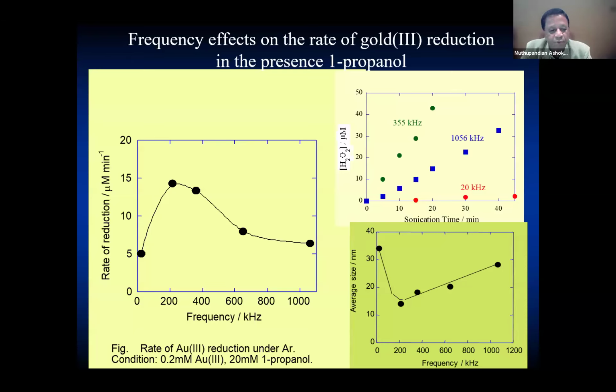So here, what I'm trying to show you is how to control the size of the gold particles that we produce. For example, if you look at this particular plot on the right-hand side at the bottom, you can see that by changing the ultrasound frequency, I can change the size of the particles that I produce. If I use 20 kilohertz, I produce large particles. If I use 200 to 400 kilohertz, I produce small particles. When I go to high frequency, like 1 megahertz, then the particle size increases.